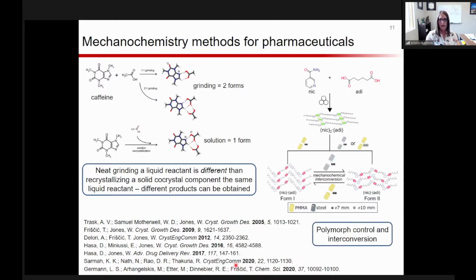The other example I wanted to highlight by Tomislav Friščić's group is looking at co-crystals of nicotinamide and adipic acid, and they were actually able to find a new co-crystalline form, as well as, which I found really interesting, by changing the milling vessel from PMMA to stainless steel and changing the size of the milling balls, they were actually able to convert between the two forms and control which form they obtain. So this again would be really advantageous if you have a polymorph that is not sort of the ideal form, but possibly you can use mechanochemistry to convert it to the other one.